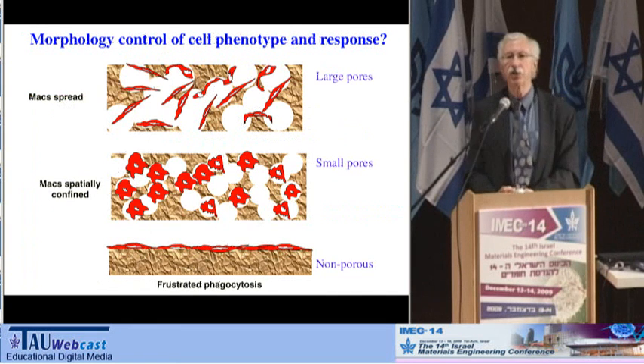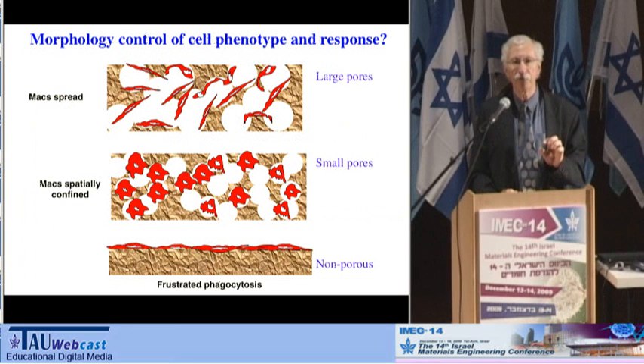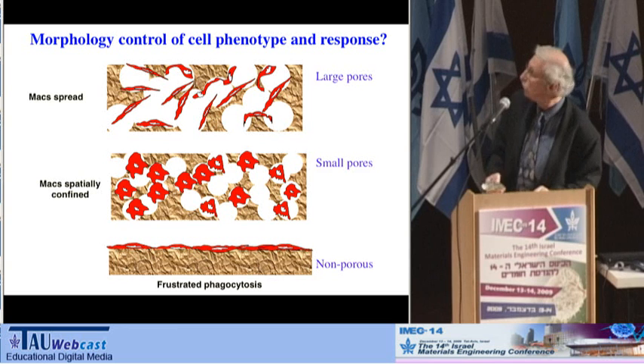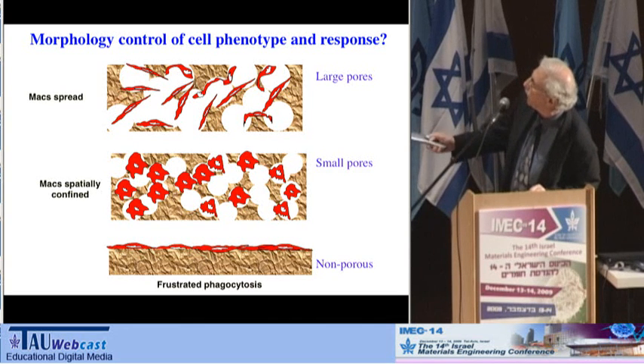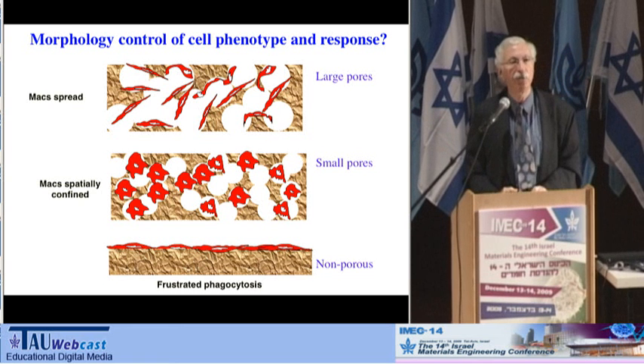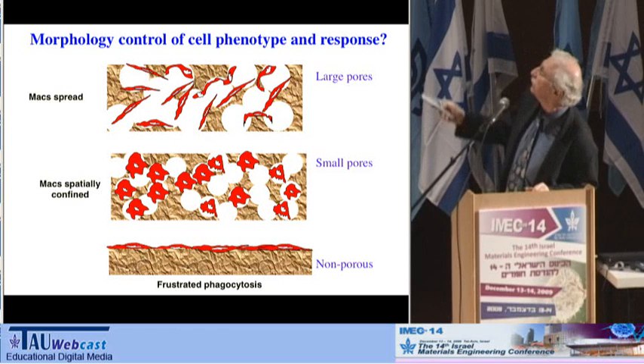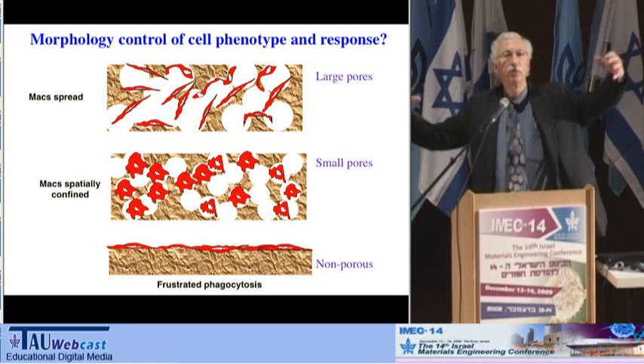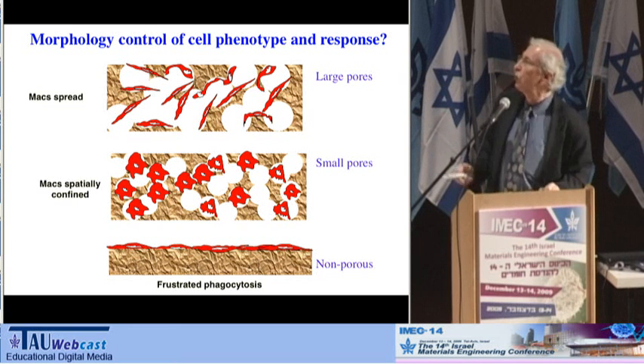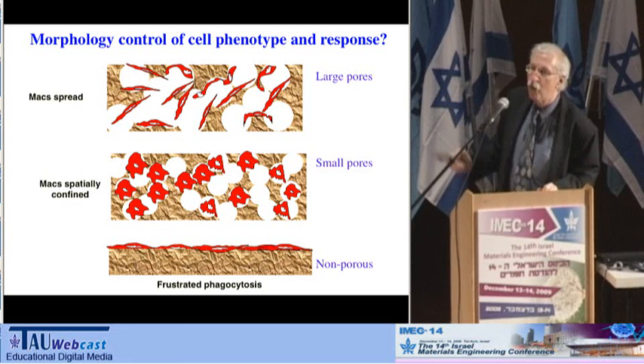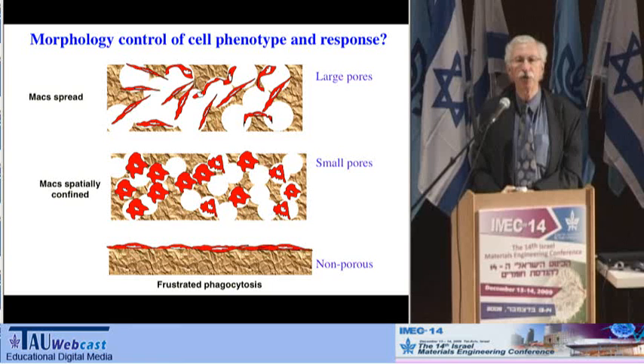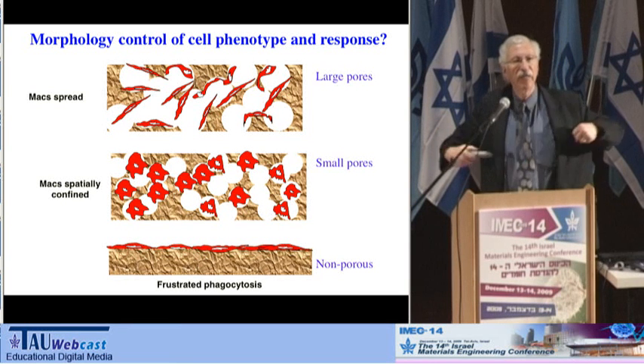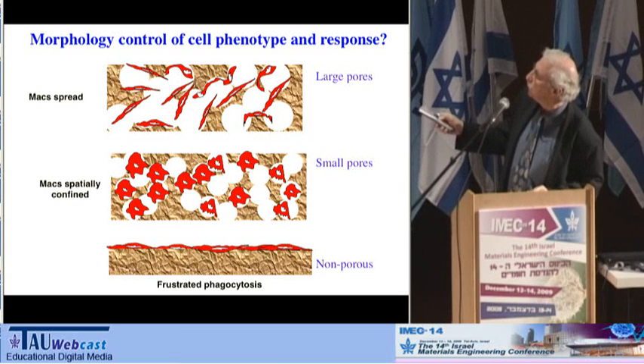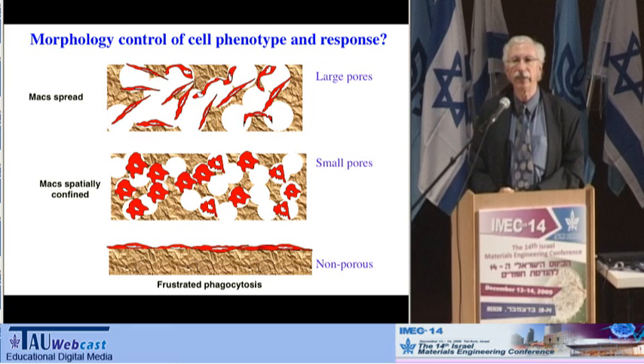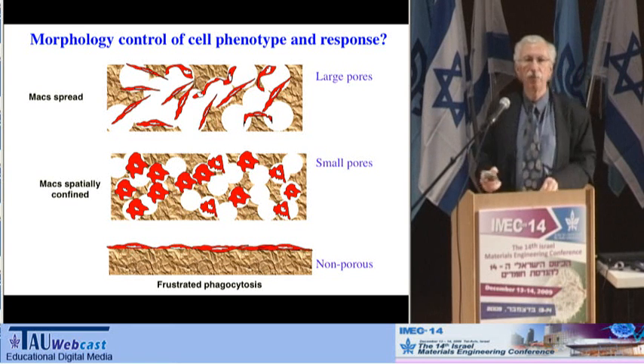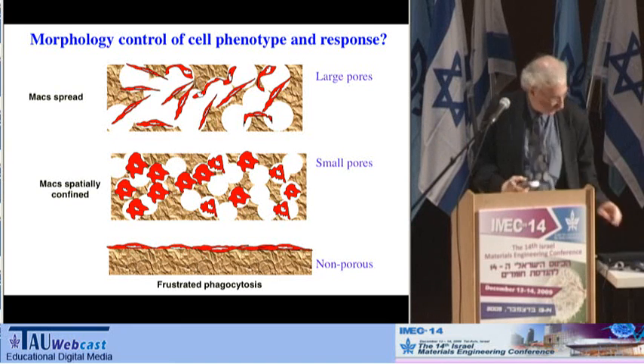And the way we're doing this is kind of interesting. Again, this is hypothesis, although we have actually the first bit of evidence that is strongly suggestive of this right now. And so on the non-porous material, this macrophage comes along, again, attempts to phagocytose or engulf the material, eat it up as foreign. In large pore materials, the macrophage has plenty of room to spread out, again, going to this futile attempt to engulf or eat the material. But in these small pores, the pores are big enough for the macrophage to go in, but not big enough for it to spread. What we believe is happening is the macrophage is being mechanically constrained, and so it's the biomechanics that's really dominating the healing process, and not a specific biorecognition clue or proteinaceous clue. And we'll get back to that point, too.